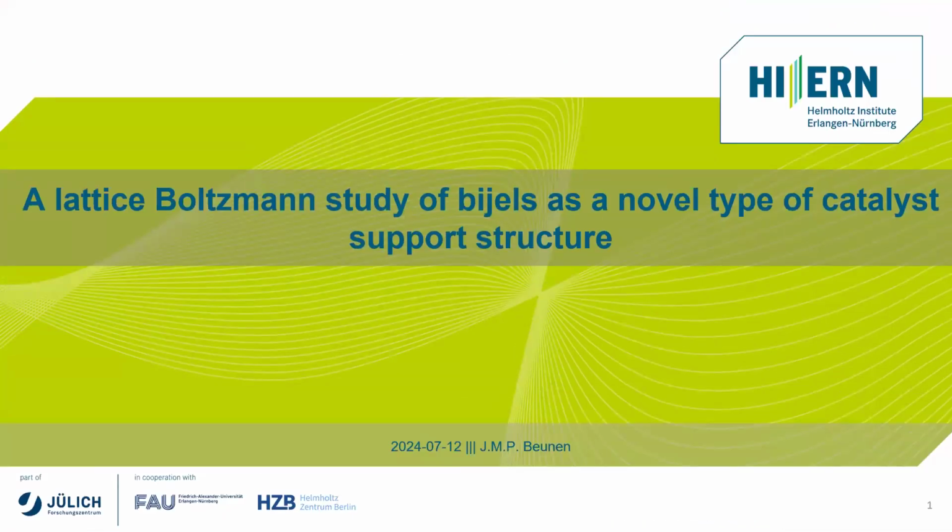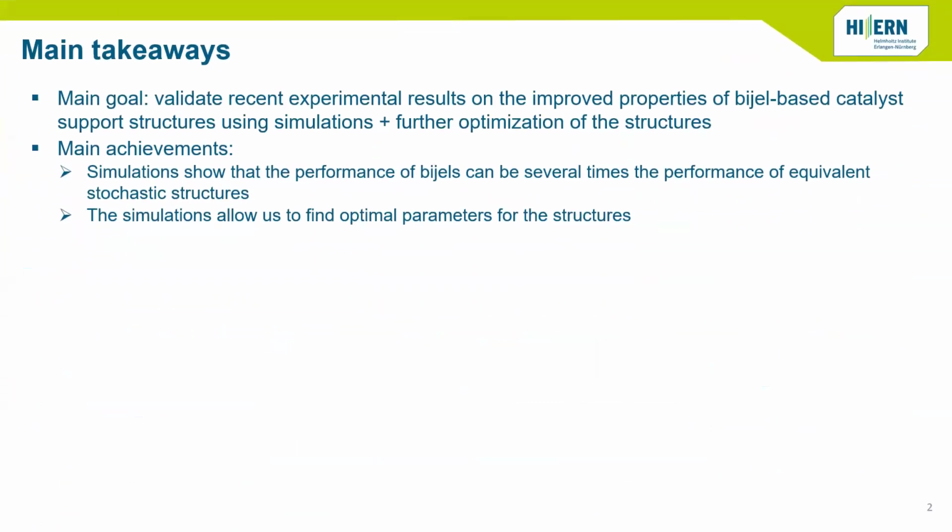All right. Then, a lattice-Boltzmann study of bijels, a novel type of catalyst support structure, is what I would like to talk about today. First, a bit of the main takeaways of the study that we did. The main goal was to validate recent experimental results on the improved properties of bijel-based catalyst support structures by means of simulations, as well as further optimization of the structures by means of simulations. And the main achievements were that the simulations show that the performance of these bijels can be several times the performance of equivalent stochastic structures, and also that the simulations allow us to find optimal parameters for generating the structures.